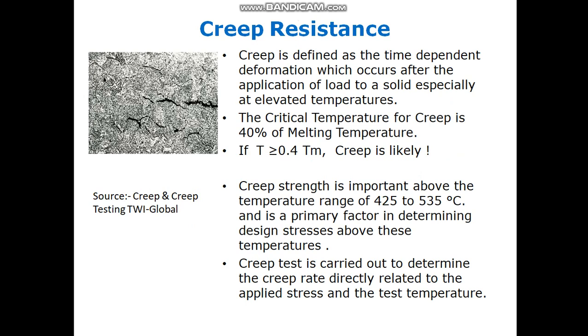Creep resistance — how can we define creep? Creep is a time-dependent deformation that occurs after the application of load to a solid, especially at elevated temperature. For creep to take place, the conditions that must be satisfied are: exposure to elevated temperature where temperature should be more than 0.4 times the melting point of the material, and the material should be under constant tensile load.